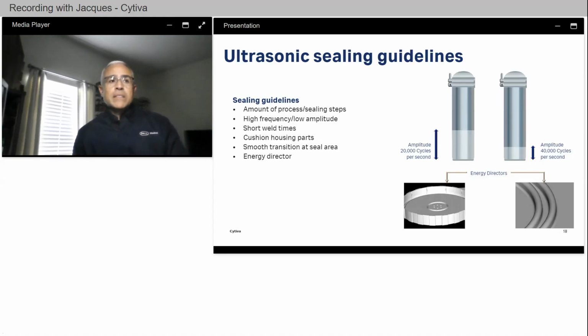We recommend sealing to an energy director rather than a wide, flat surface. These energy directors should have a radius to avoid a sharp edge that may damage the filter membrane when ultrasonic welding the membrane directly to the housing component. You can see from the pictures on this slide, there are radiuses on the tops of each of these circular energy directors. And lastly, successful ultrasonic sealing requires the user to optimize the equipment's frequency and amplitude during the process development, and then ensure these conditions can be sustainable during production.